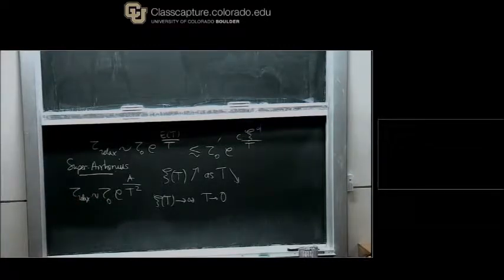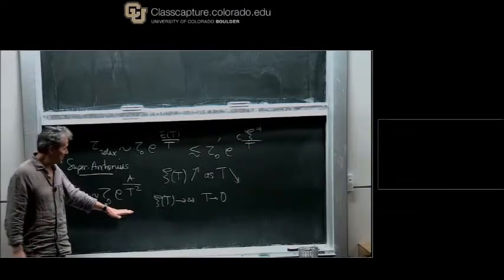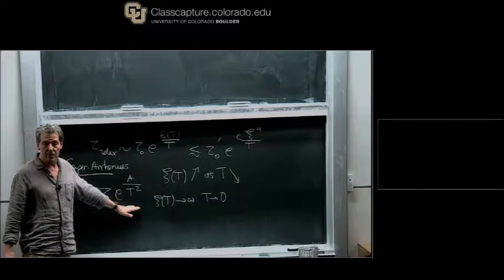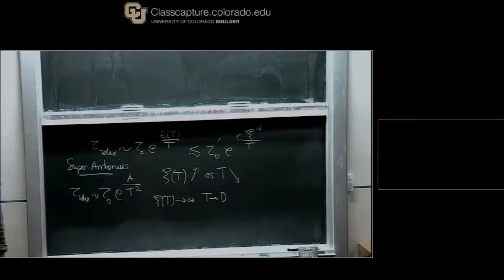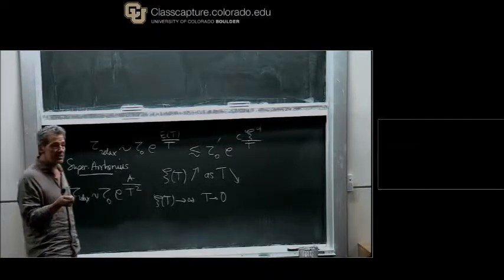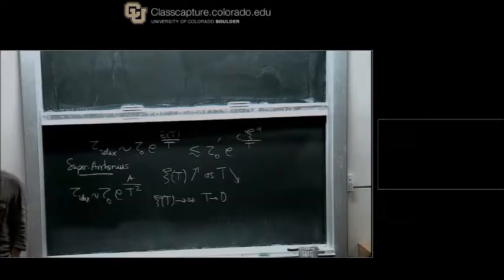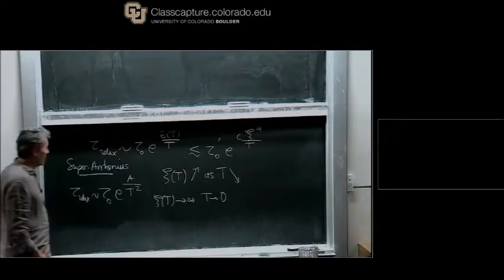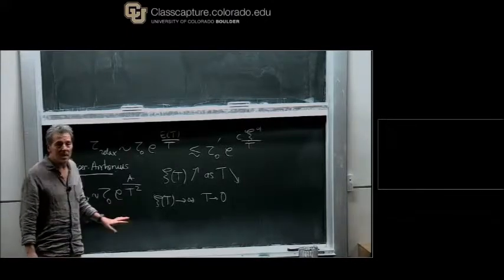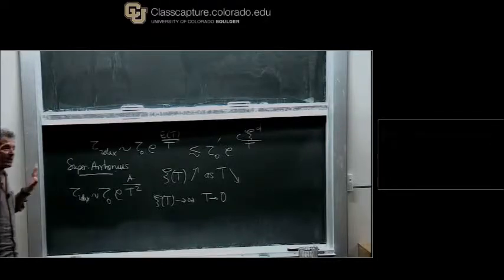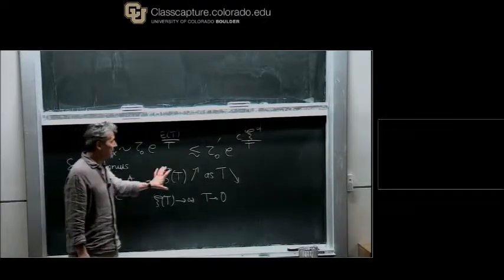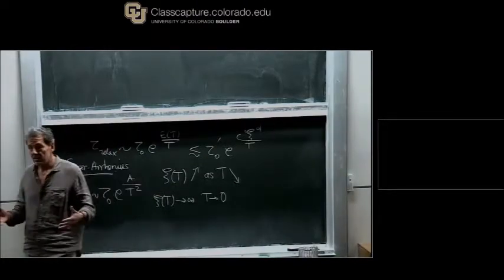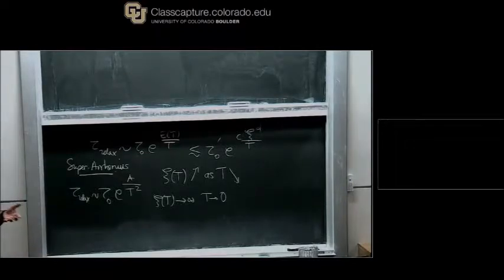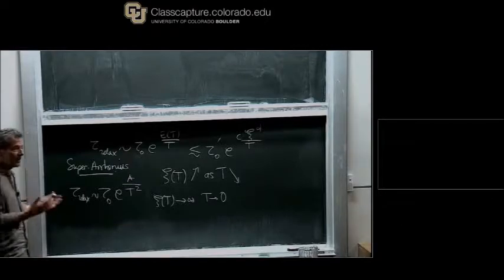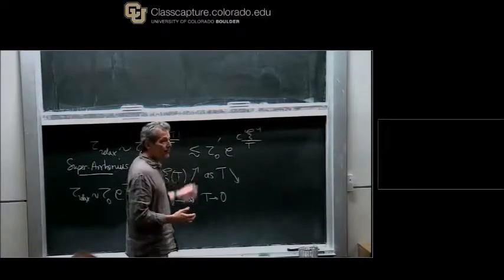And again, even if you're super Arrhenius, even if the divergence is only at 0 temperature, then you will have nonetheless a length scale like this, a static length scale, that needs to diverge at 0 temperature. So again, this is telling you that those theories that try to do away with any sort of static length scale while still having super Arrhenius behavior of this type, well, maybe they're missing something. What it doesn't tell you, again, is how big is this length scale when you are in the observation range, that is, when you're above the glass transition Tg. Okay, so this is a matter of principle.